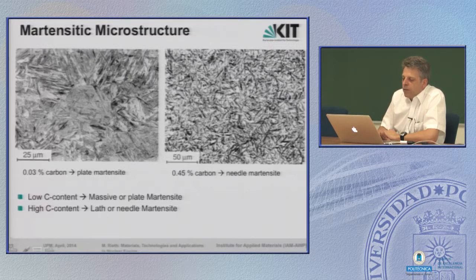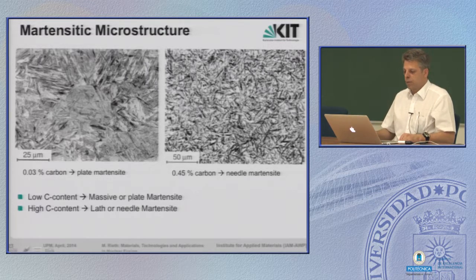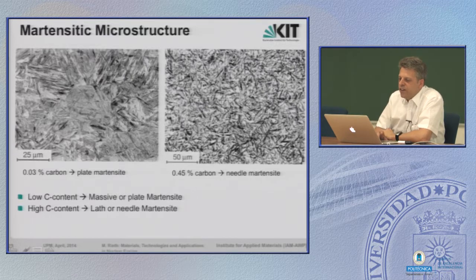Depending on the carbon content, whether you have a higher content or a lower content, in the microstructure and optical microscope pictures, it looks like that. Very, very fine structured subgrains, or whatever you want to call it, appear. And you cannot easily recognize these former austenite grains. If the carbon content is much lower, here is an example for 0.03% carbon. That's about the carbon range for Eurofer steel. You still can see where the former austenitic grains have been, but inside these grains we have this severe change in microstructure, and this is again martensite.